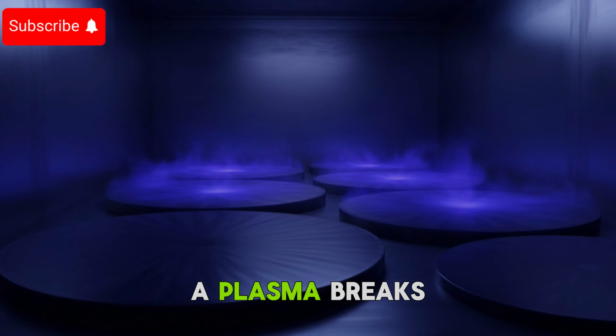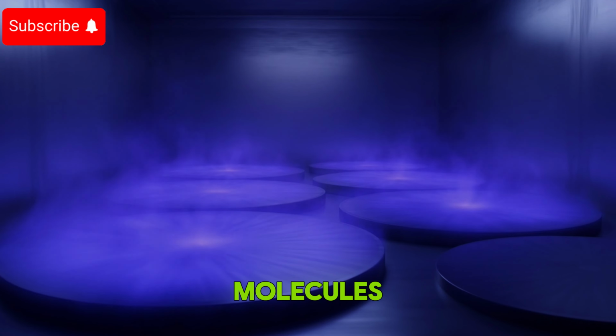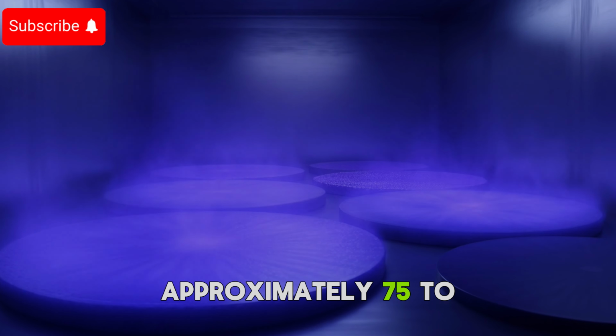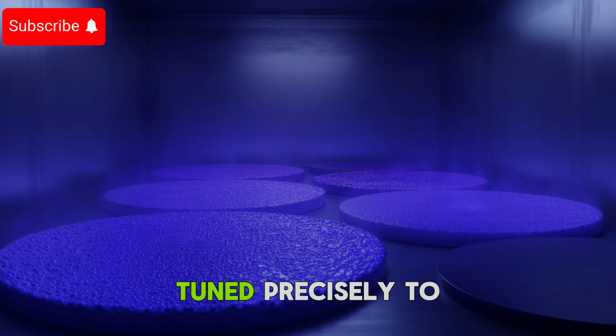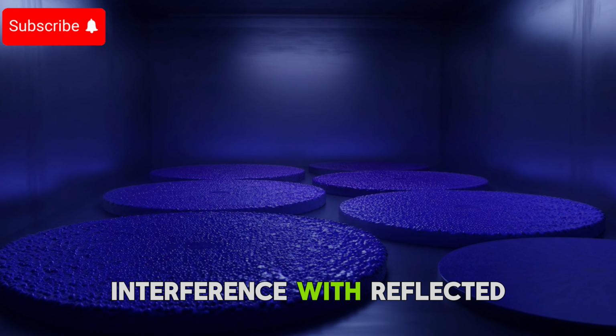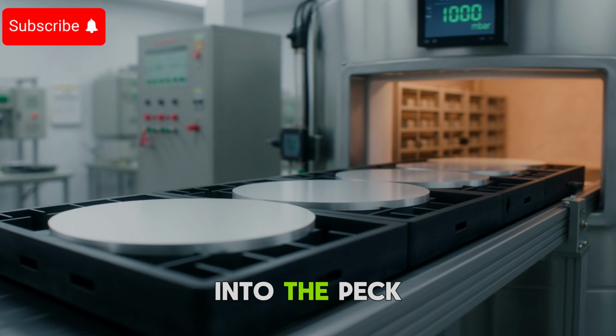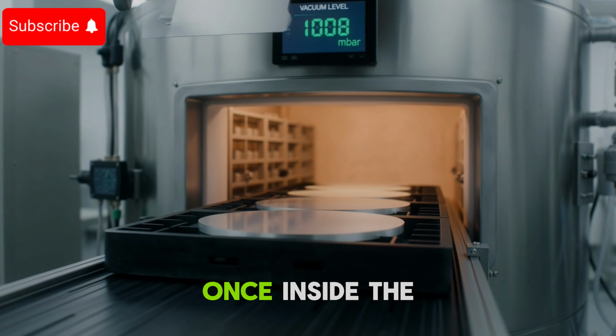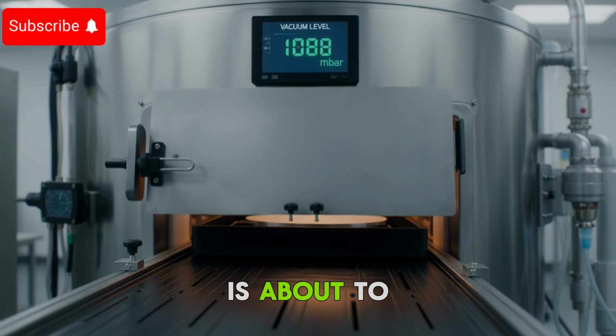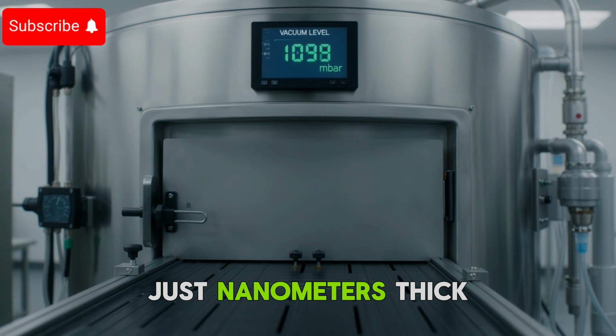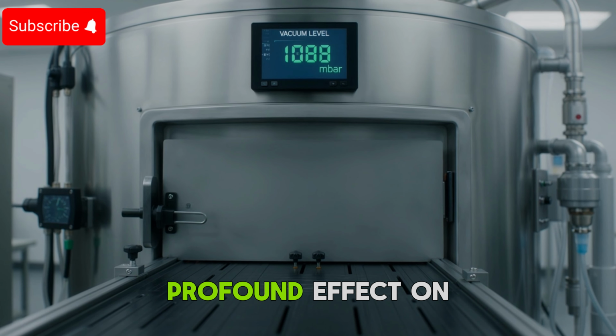Inside the chamber, a plasma breaks down silicon nitride molecules, building a uniform layer approximately 75 to 80 nanometers thick on the wafer surface, tuned precisely to cause destructive interference with reflected light. Wafers are loaded into the PECVD chambers through automated ports. Once inside, the chamber's silane gas flow is about to begin, building a coating just nanometers thick but with a profound effect on the finished cell's performance.